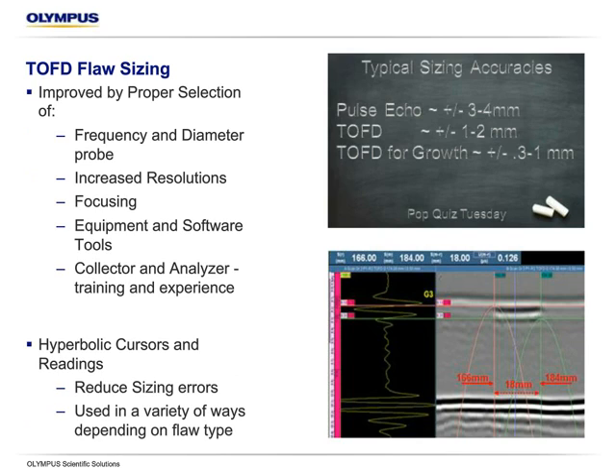All right, flaw sizing. Just a few considerations. If we looked at a round robin, and it's going to vary by a lot of the variables, but if you took a bunch of trained operators for really any pulse echo ultrasonic technique, and a group of qualified trained TOFD guys for flaw detection, you typically get these numbers on most studies: most pulse echo techniques are going to give you a sizing accuracy of about 3 to 4 millimeters in length and height. That's typical, not that it can't be much better under the right variables. TOFD, on the other hand, in general will probably improve upon that, to 1 or 2 millimeters, with the potential to do much better for flaw sizing.